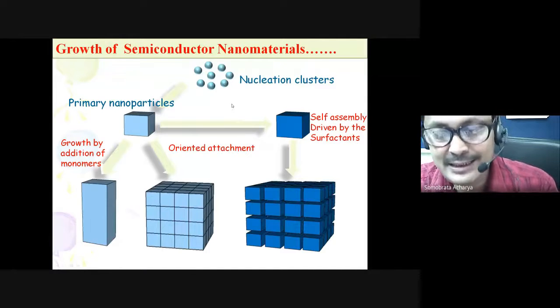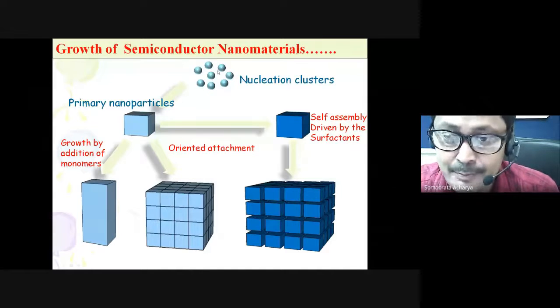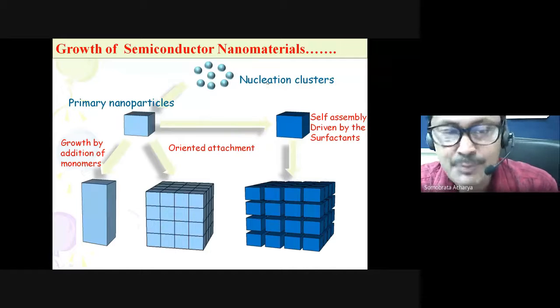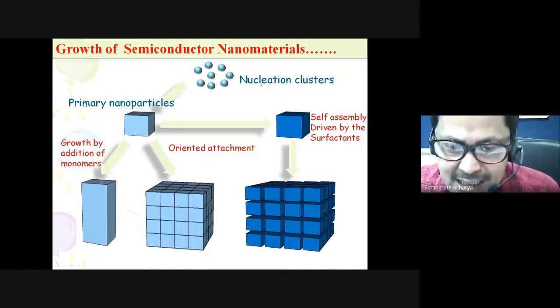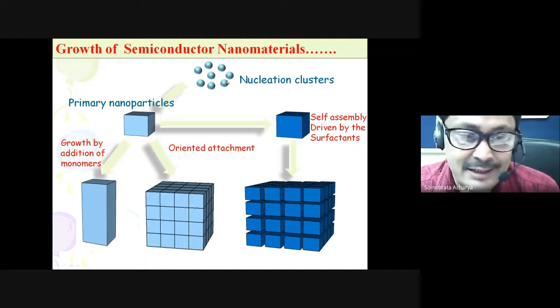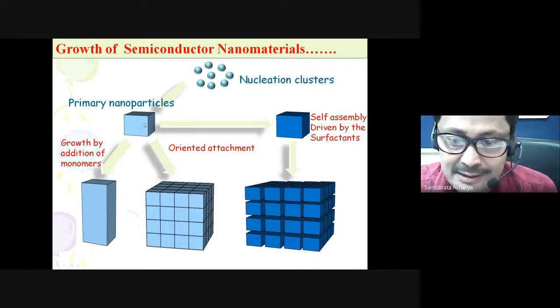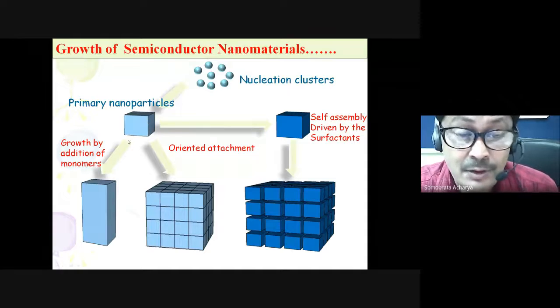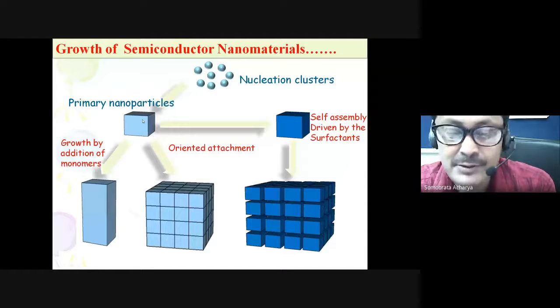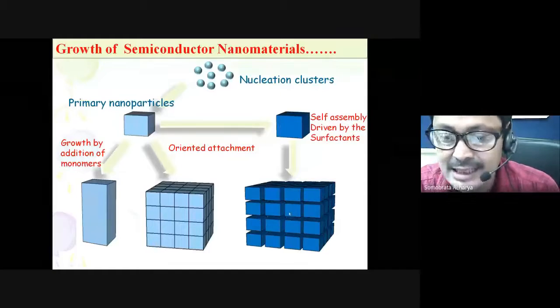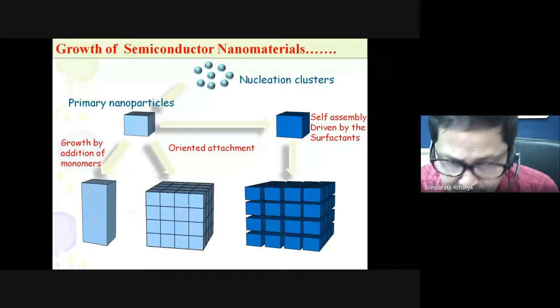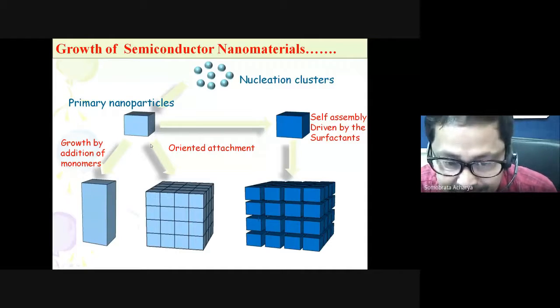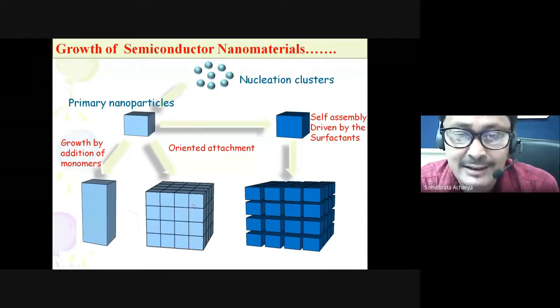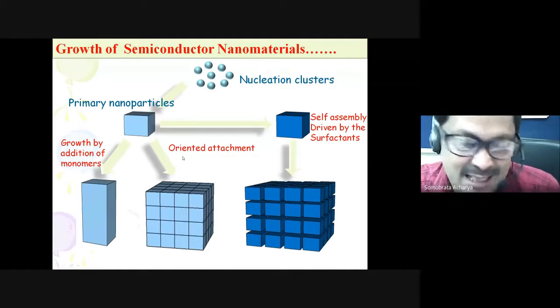So once you are injecting the ingredients within your reaction system, first the nucleation occurs. So you'll have small clusters of those elements there. And then once you are continuing the reaction, these small clusters will come together to form a moderate size of nanocrystal there. And if you continue the reaction further, many things can happen. These primary nanocrystals self-assemble within your reaction system, so they can self-assemble like that. Also, if you don't have the ligand on this side, these nanocrystals can be adjoined during the reaction to form the oriented attachment assembly.